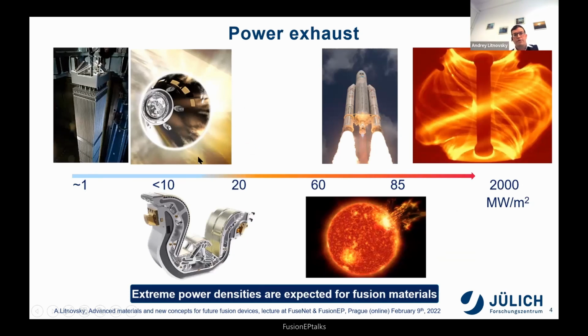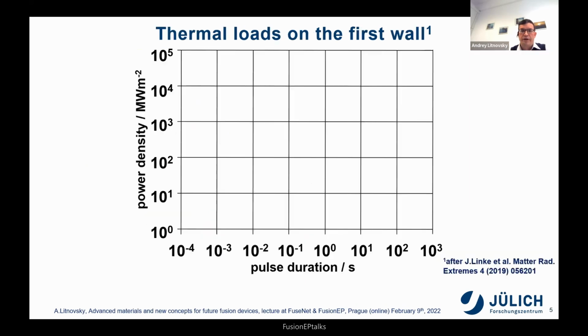You can see that 20 megawatts per square meter actually corresponds to the surface of a space vehicle during re-entry processes. And the transient effects like disruptions can feature up to 2 gigawatts per square meter, which is, let's say, a characteristic feature of fusion devices. So these are really quite important and quite challenging numbers that the materials will be facing.